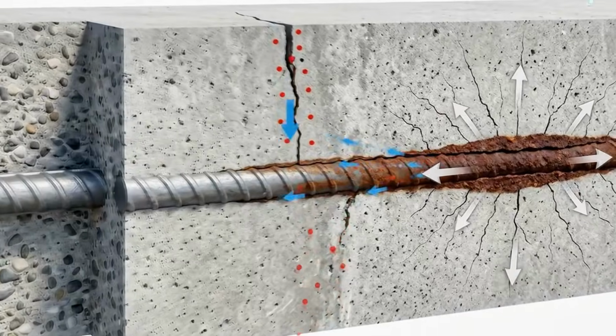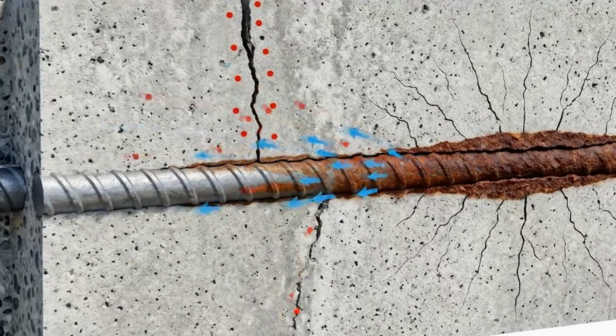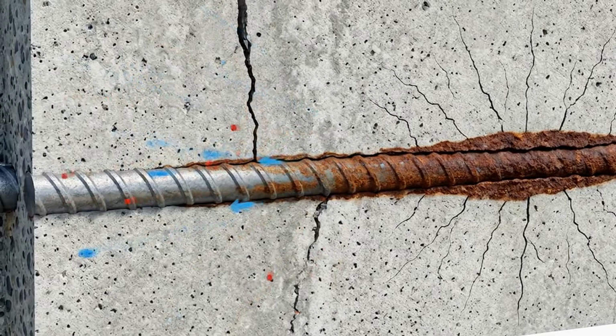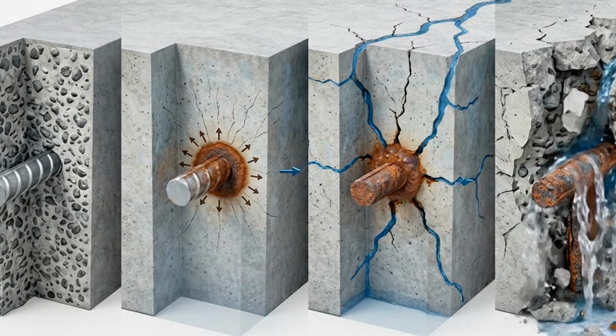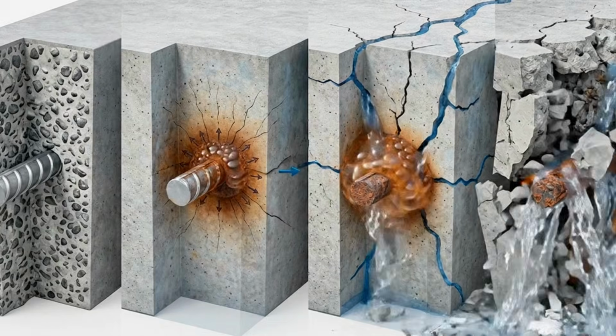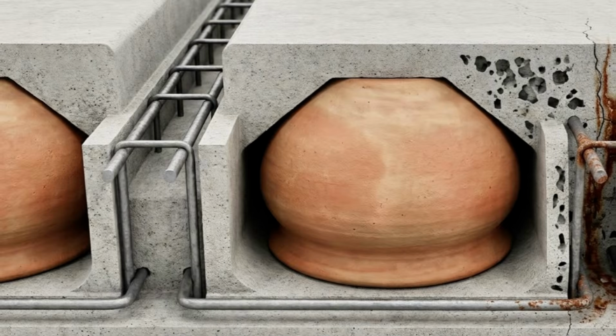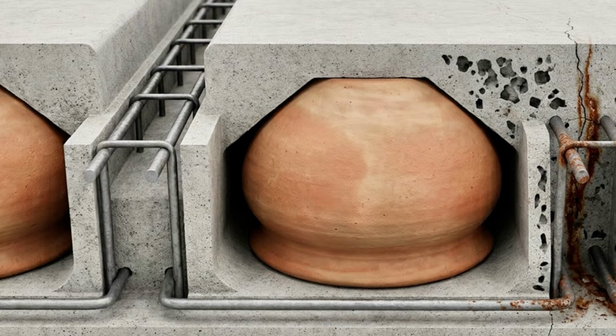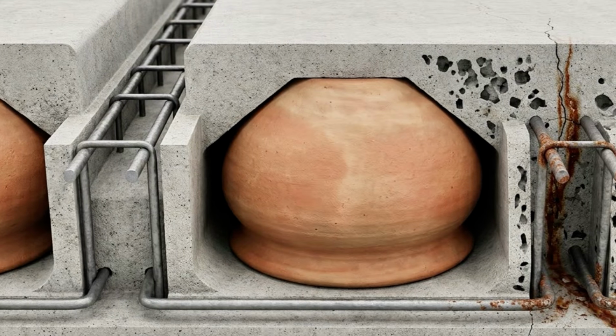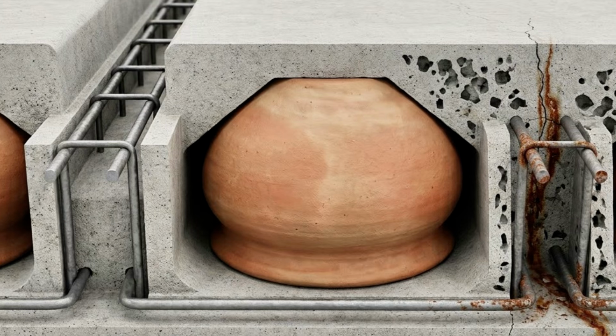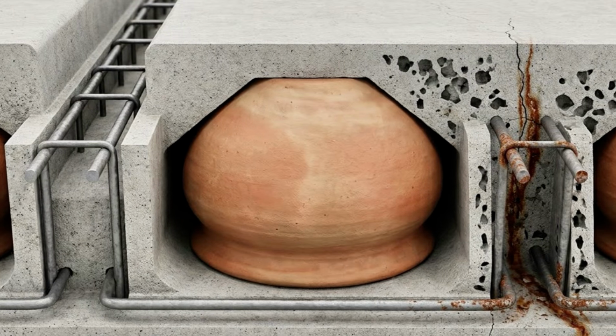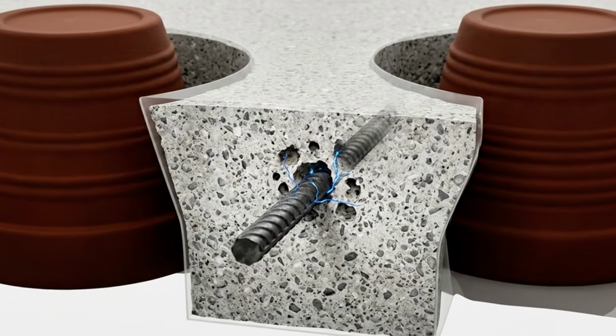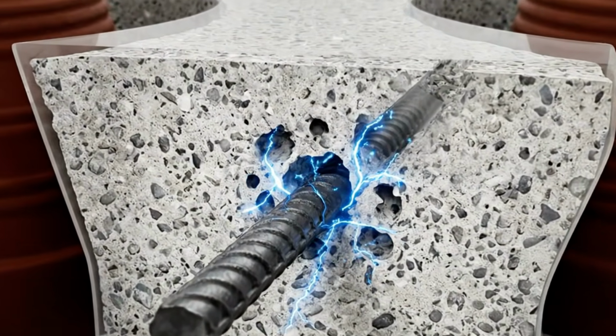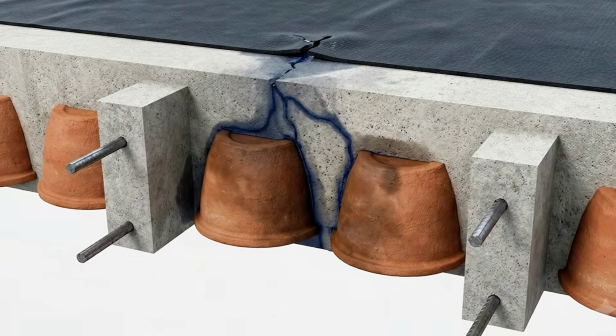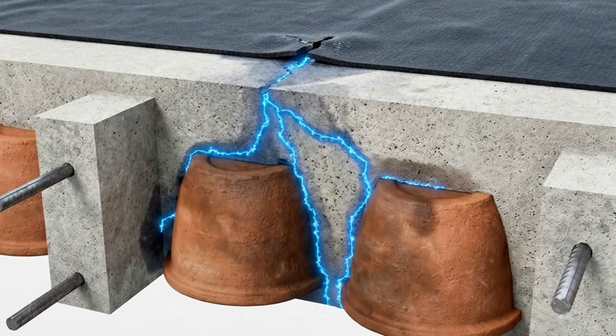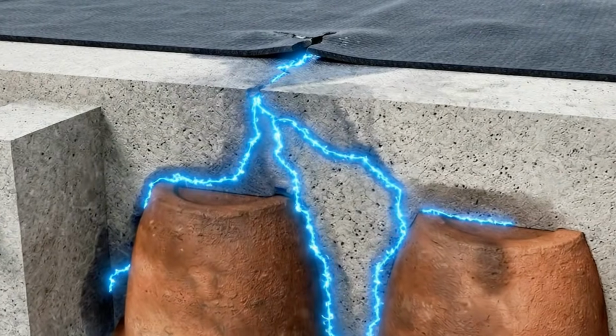Rust occupies more volume than the original steel. As it expands, it pushes against the concrete surrounding the bar. Over time, that pressure can create cracks, loosen the concrete cover, and accelerate further water penetration. A filler slab does not automatically create this problem, but poor detailing can make it harder to detect and harder to repair. If a filler is placed too close to the reinforcement, the concrete cover between them may become too thin. If wet concrete does not completely fill the narrow spaces around the bars, hidden voids can remain. If the roof membrane fails, porous clay may absorb moisture and keep parts of the assembly damp for longer.